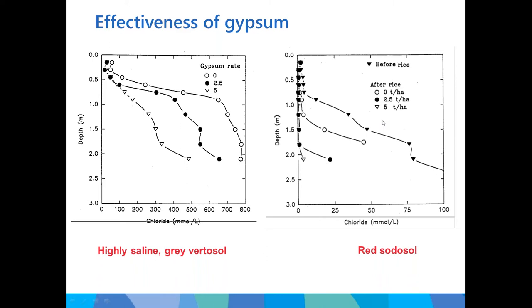In the sodosol, it's a leakier soil. And so before rice, we've got significant amount of salt below a metre. Even with just a rice crop, we've lost some of that chloride, but when we put 2.5 and 5 tons on, we lose even more down to 2 metres.